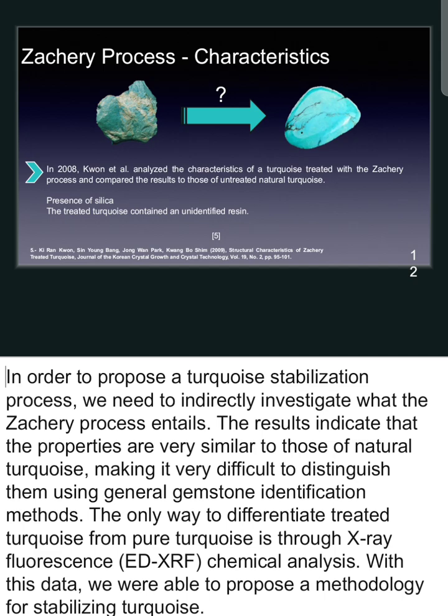In order to propose a turquoise stabilization process, we need to indirectly investigate what the Zachery process entails. The results indicate that the properties are very similar to those of natural turquoise, making it very difficult to distinguish them using general gemstone identification methods. In 2008, Kwon et al. analyzed the characteristics of a turquoise treated with the Zachery process and compared the results with those of untreated natural turquoise. They concluded that it has a presence of silica, and the treated turquoise contains an unidentified resin. The only way to differentiate treated turquoise from pure turquoise is through X-ray fluorescence chemical analysis. With this data, we were able to propose a methodology for stabilizing turquoises.